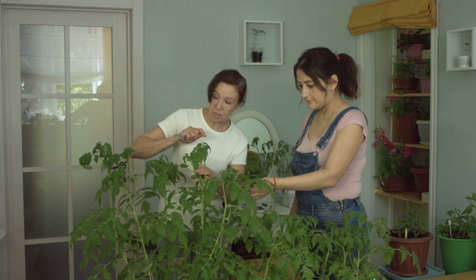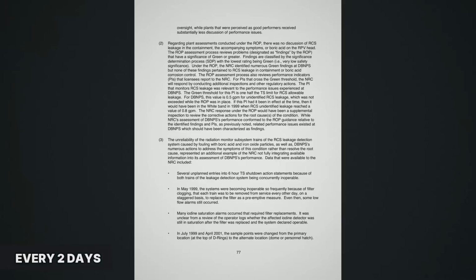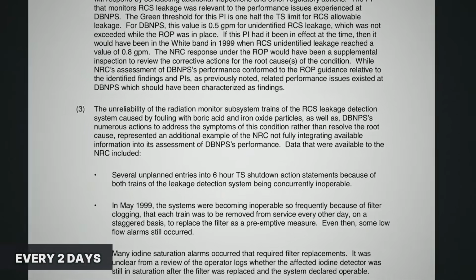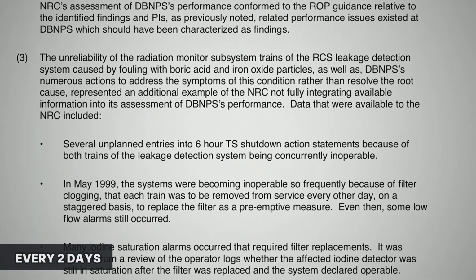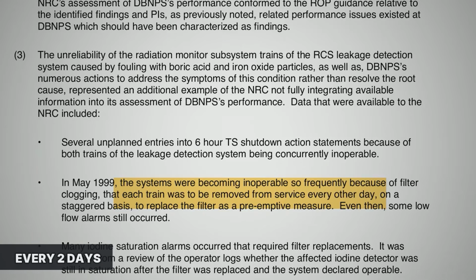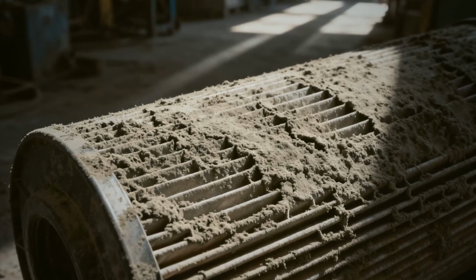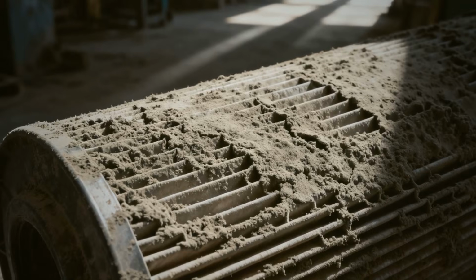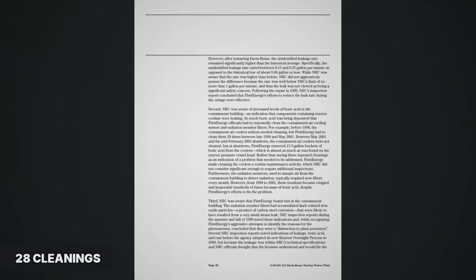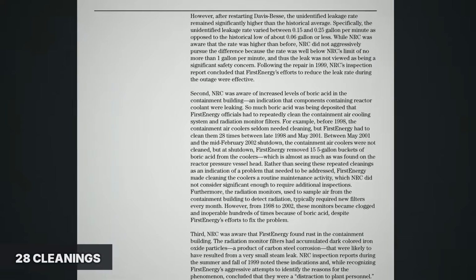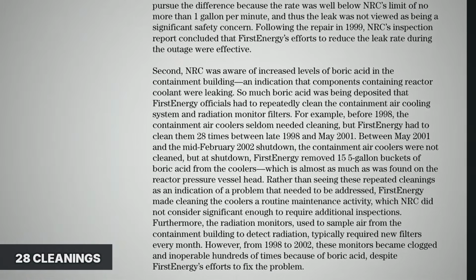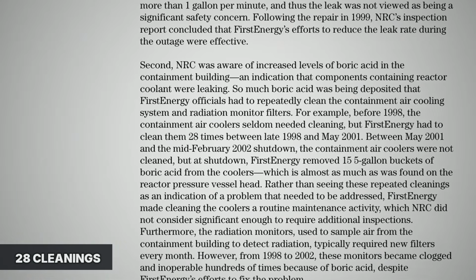Then the plant starts complaining in a different language. Inside containment, there is a radiation monitor with filter elements. Those filters normally get changed about once a month. By May of 1999, they were being changed every 2 days, 15 times the normal rate. Something was loading those filters with particulate continuously for months. The containment air coolers tell the same story louder. Before 1998, according to the record reviewed by the Government Accountability Office, those coolers seldom needed cleaning.